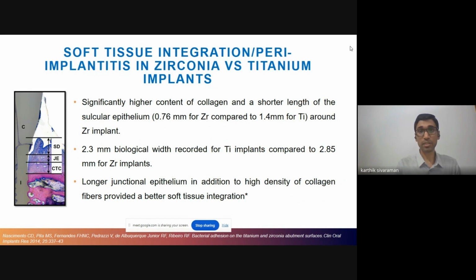Now, those were the similarities, but there are a few differences as well. There was a significantly higher content of collagen and a shorter length of the sulcular epithelium around zirconia implant. So around 0.76 mm for zirconia compared to 1.4 millimeter for titanium. Also, the biological width was found to be more, 2.85 millimeter for zirconia implant compared to 2.3 millimeter for titanium implants. So the longer junctional epithelium, in addition to the high density of collagen fibers, are said to provide a better soft tissue integration and better resistance to any bacterial ingression, resulting in lower chances of